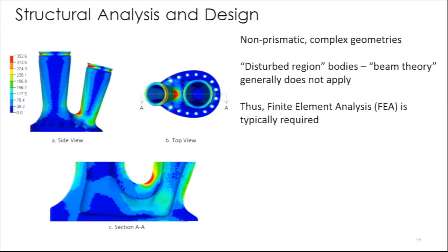Once we understand the stresses in the castings, then we'll set non-destructive examination criteria for the manufacturing process. So that will tell the manufacturers of the castings what is the largest indication that we can accept at the various regions of the casting. And in the event that any of those regions show an indication that's larger than our criteria, that area would be weld repaired in process prior to the final stress relief. So at the end of the day, we have a monolithic cast steel component that simultaneously meets our quality criteria and is capable of resisting the forces that are applied to it.